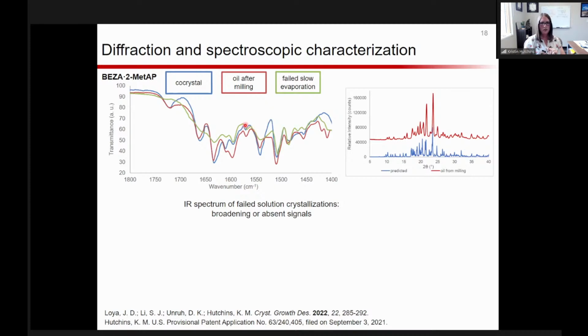And so by IR spectroscopy, in the case of the 2-methyl aminopyridine, what you see in the IR is that you either have signals that are absent or broadened, whereas the oil directly from milling correlates really nicely to the co-crystal. So clearly that product from milling is giving us co-crystalline material, even though it's not necessarily a solid that's easy to work with. By powder X-ray diffraction as well, if you look at the predicted pattern and compare that to the oil directly from milling, you can see that that oil is actually quite crystalline, has really nice diffraction, and shows really good correlation to the simulated pattern as well.